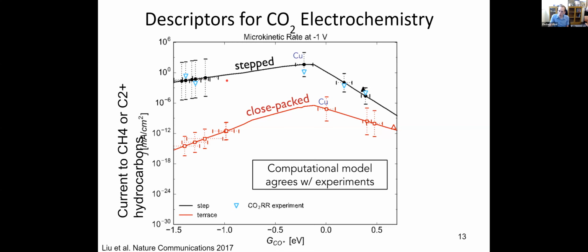And so we can sort of rationalize what's going on with copper by saying, well, it's the only one that appears to have an intermediate binding energy of CO, where you're strong enough that you keep it around, but weak enough that you can do something cool with it and it doesn't just poison the surface. The natural question is to say, look, why is there this huge gap between all of these things on the left-hand side and the right-hand side? Why is copper sitting there? And what if we could find other materials that are like copper sitting near the top of the volcano? Again, a very simplified picture, but a very interesting material science question.